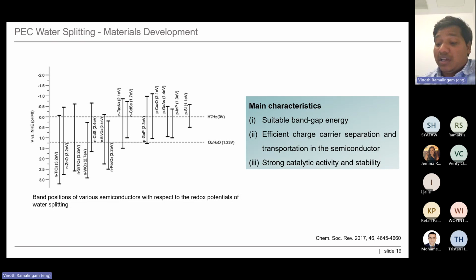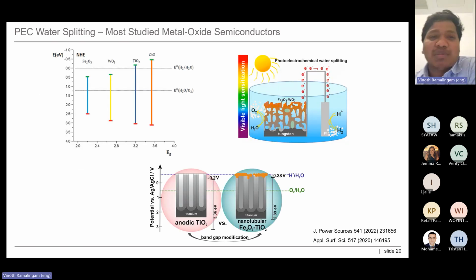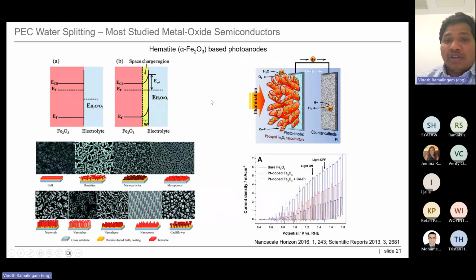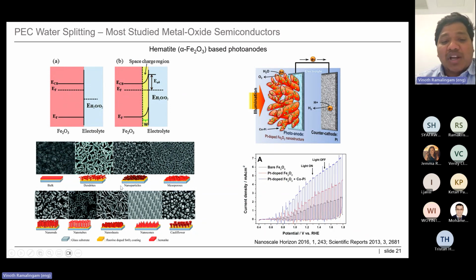So these are some of the most studied metal oxide semiconductors, for example iron oxide, tungsten oxide, titanium dioxide, and zinc oxide. These are some of the examples from the literature where they have been used as photoelectrodes for water splitting reactions. Fe2O3 has been widely used because of its excellent band gap for the water oxidation reaction. And you see that different nanostructures have been developed, from bulk to nanoparticles, nanotubes, and nanosheets of different structures, that can help to improve the light absorption ability of the photoelectrode as well as the overall performance.